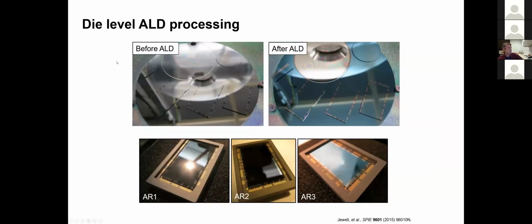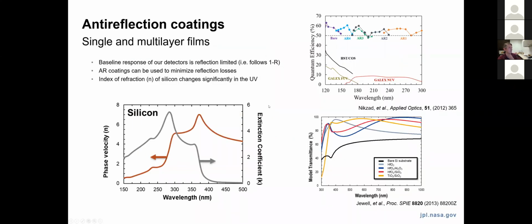In some cases, it's advantageous to perform the optical coating part of the process at the die level so that we get a wider sampling of coatings to choose from for a given number of devices on a wafer, for example. So this ALD processing can be done at the die level as well, showing here the evolution of some AR coatings that I'll describe later were used for the Fireball balloon mission, allowing us to optimize as we go. So let's talk a little bit about anti-reflection coatings. I mentioned how the delta doping process can get us this 100% internal quantum efficiency. So now we're concerned with the losses from silicon due to reflectance.